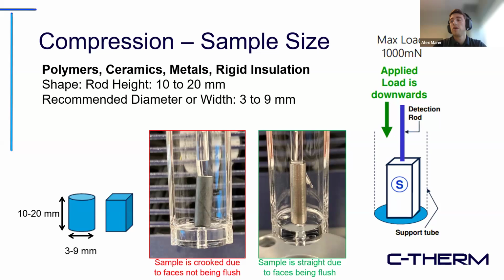The reason for the recommended diameter from 3 to 9 is because as the sample gets wider, it creates the possibility for a non-uniform temperature distribution. So you can run into a possibility if the sample is too thick where the temperature on the outside of the sample is way hotter than the temperature on the inside, which decreases the accuracy. And if your material is going through a transition like a glass transition, it's possible that the inside is still very sturdy and in the glass state, but the outside is in the rubbery state, so it can give non-ideal results in that way.